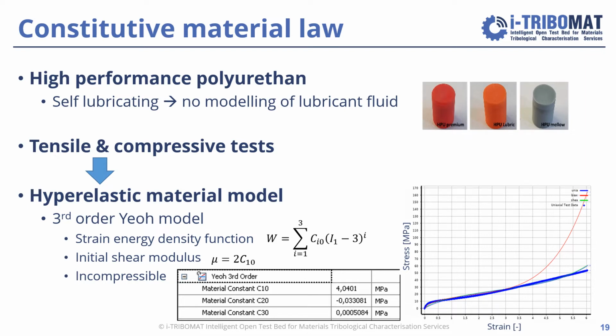So what do we do? We use tensile and compressive tests of each of those materials and fit a material model to it. We found out that a hyperelastic material model is most appropriate, and from the group of hyperelastic models, the third order Yeoh model turned out to have the best fit in the region of interest. So here you can see the strain energy density function, and here the parameters we assigned as we assumed the material to be incompressible. All the other parameters are 0.